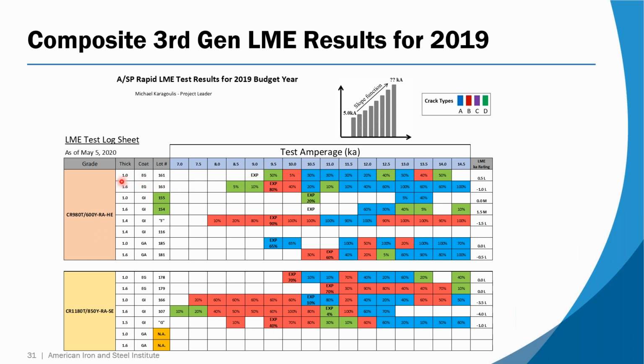This first material was a 1 millimeter EG 980 material, lot number 161. It had expulsion at 9 kiloamps, and all the LME occurred above expulsion. A little bit of red, and the rest of it was blue. So that's how you interpret those results.